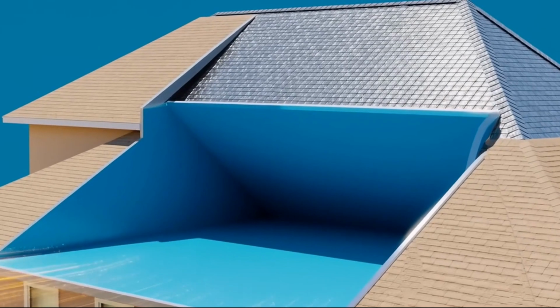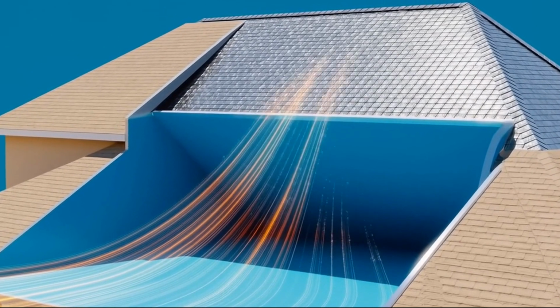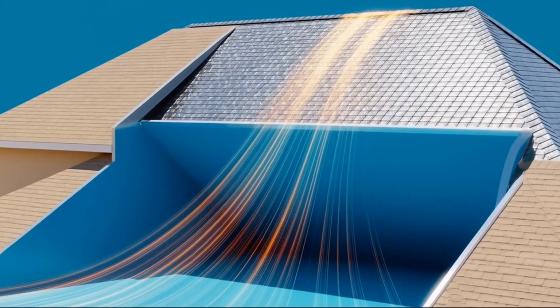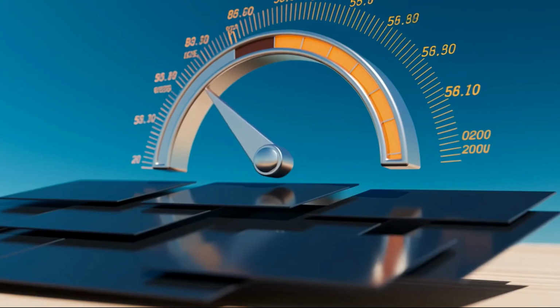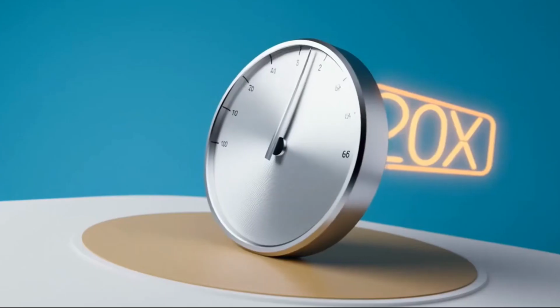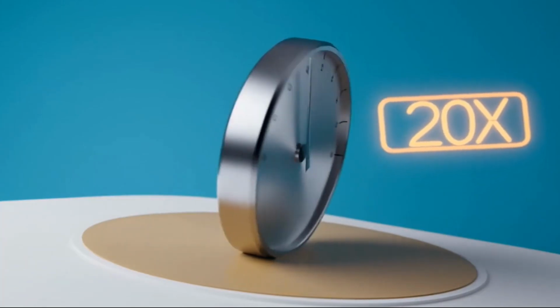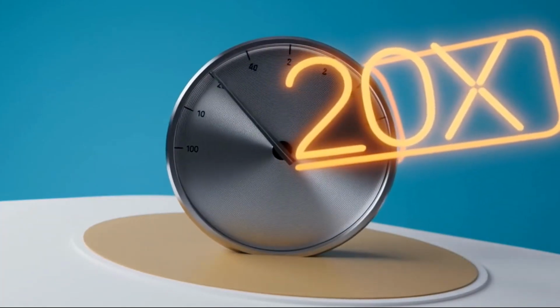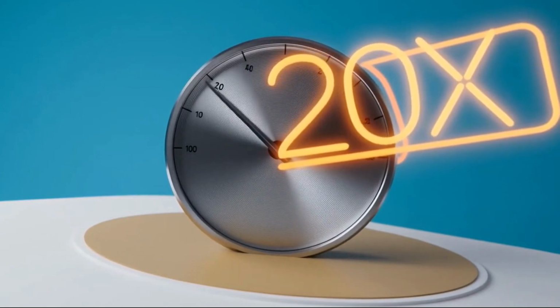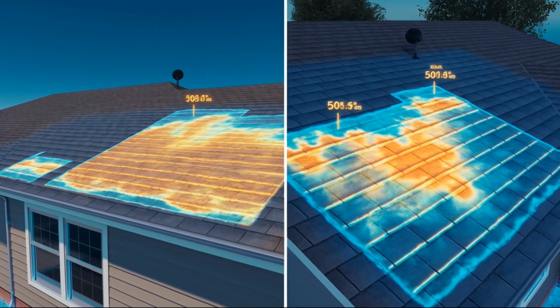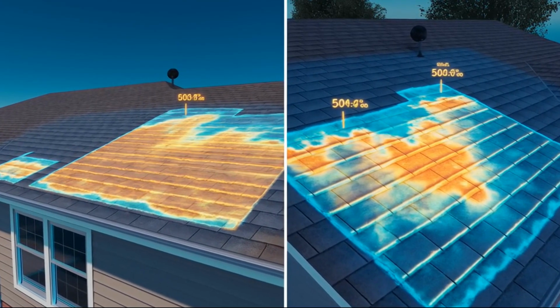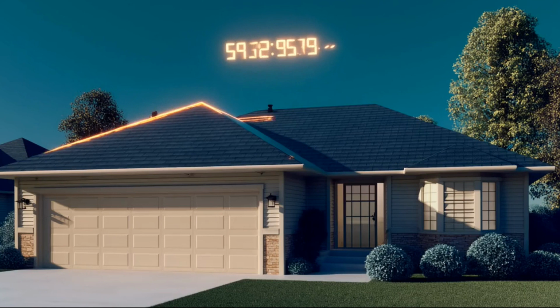Good white roof coating, 90% emittance. That means whatever heat sneaks in, the surface radiates it back out almost as fast as it arrives. Combine high reflectance and high emittance, you get Solar Reflectance Index, or SRI. A black shingle scores 5. Bright white elastomeric coating scores over 100. 20 times the difference in how the surface handles solar energy. On a typical summer day, that difference shows up as a 50 to 60 degree Fahrenheit gap between roofs. Measured at noon in direct sun on the same house.